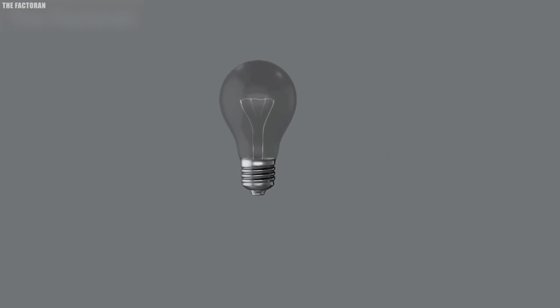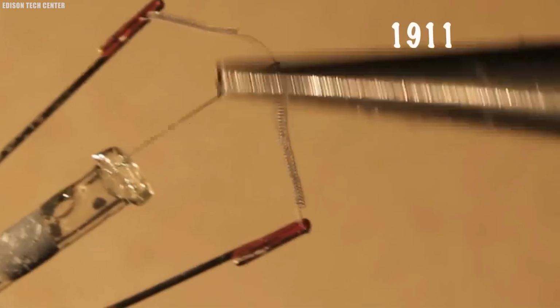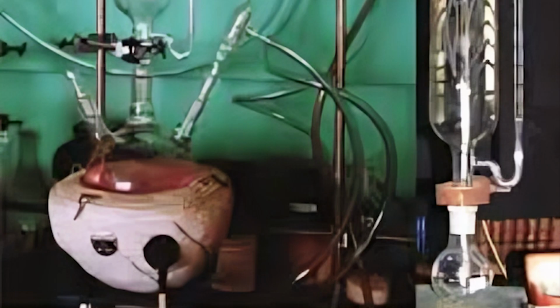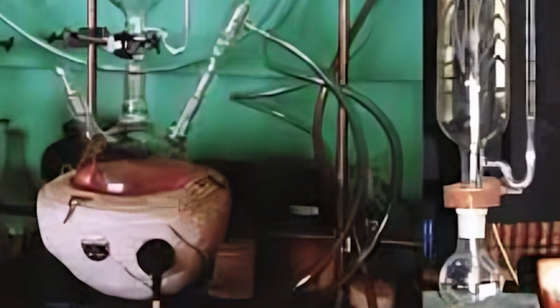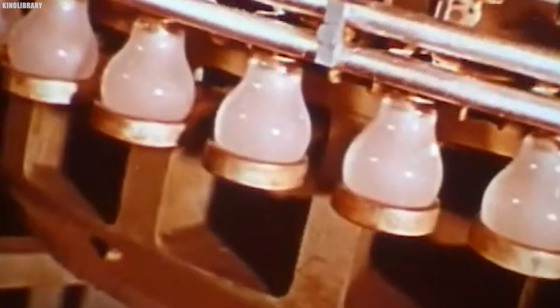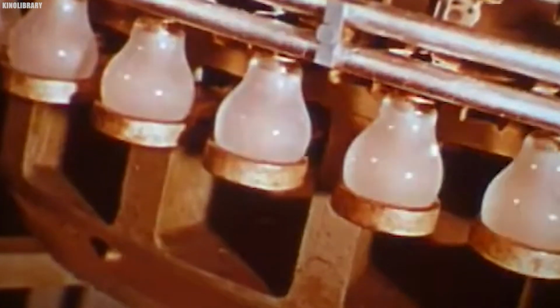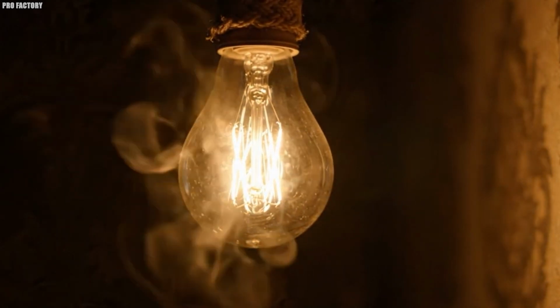The completed mount assembly was inserted into the glass envelope and positioned centrally before the neck of the envelope was reheated and collapsed onto the glass stem, forming an airtight junction between the two components. The integrity of this seal was critical. Any leak path, however small, would allow atmospheric oxygen to enter the envelope during operation and oxidize the tungsten filament within seconds of the lamp being switched on.